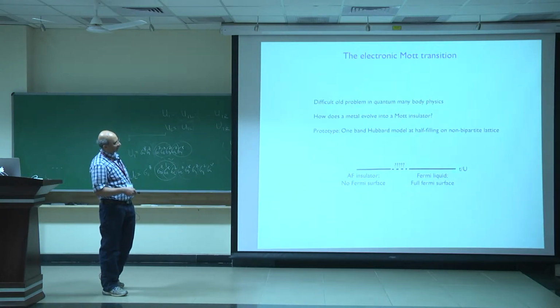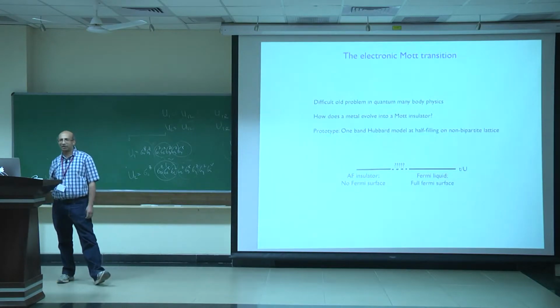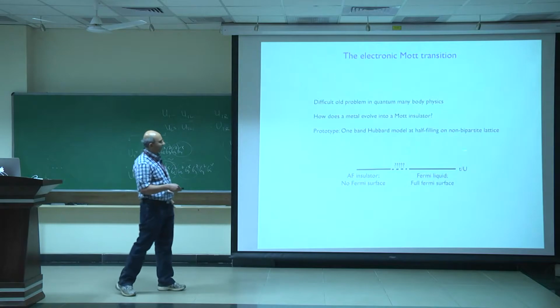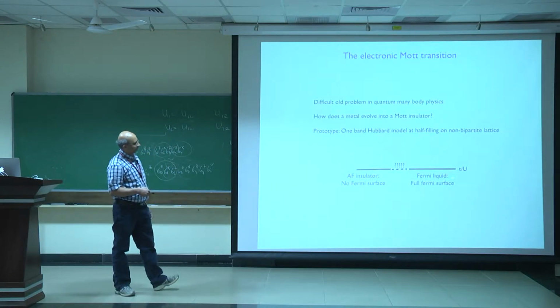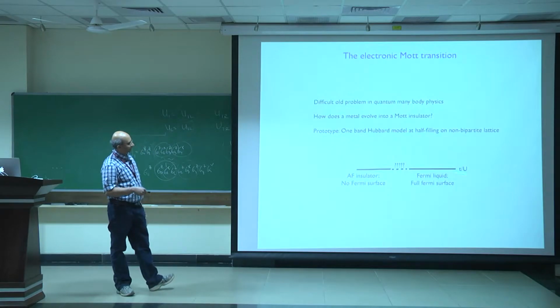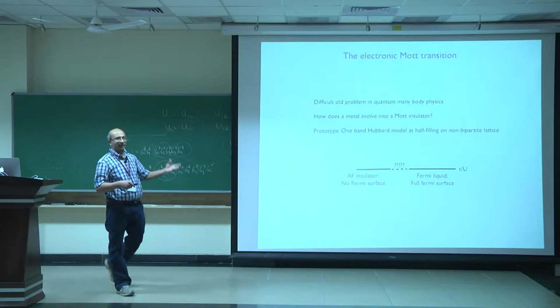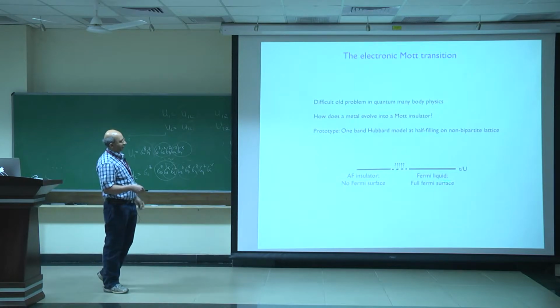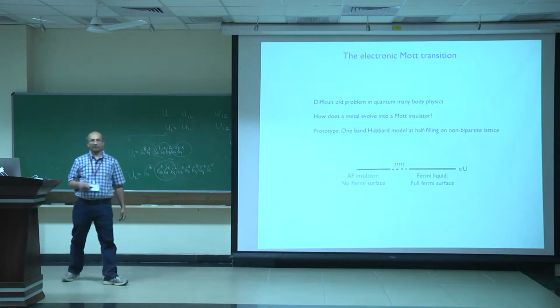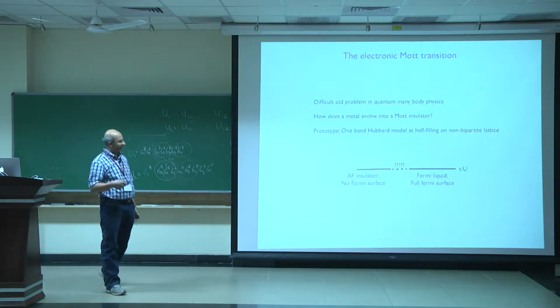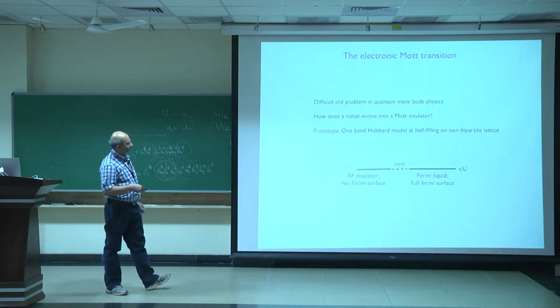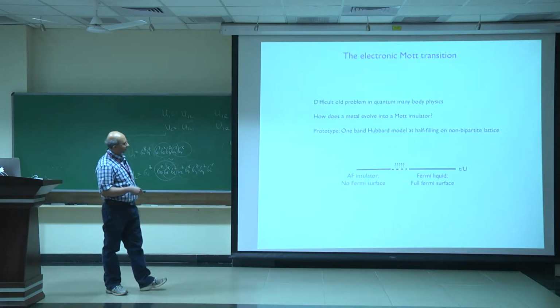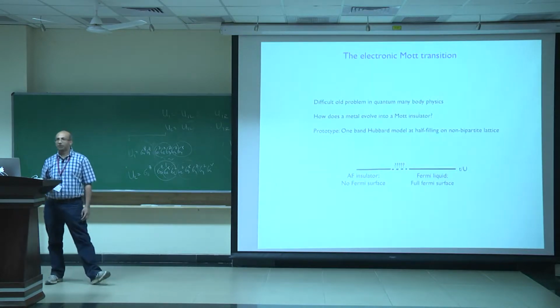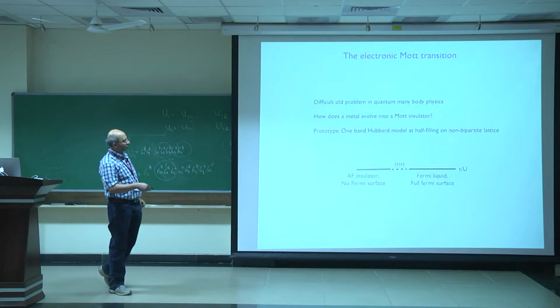So the Hubbard model is characterized by 2 parameters, T and U. So it's 1 dimensionless parameter, T over U. If T over U is big and you're on a non-bipartite lattice, the ground state will be a Fermi liquid with a full Fermi surface, which corresponds to the density of electrons per unit cell. If T over U is small, you will get a Mott insulator, and this Mott insulator will have spin exchange. And even on a triangular lattice, it goes into an antiferromagnetic ordered state. So you get an antiferromagnetic insulator, and of course the insulator has no Fermi surface. And the question about the Mott transition is how to evolve between these 2 extremes.